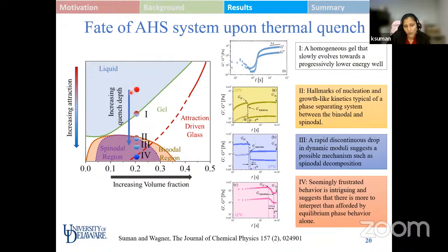As we increase the quench depth, we enter the two-phase region. In region 2, we saw a sudden decrease in the modulus value, followed by a continual increase in the modulus value, which suggests that continuous nucleation and growth-like kinetics is happening in the material, and therefore the material can be supposed to lie between the binodal and the spinodal region. With further increase in the quench depth, we enter region 3, where the sudden decrease is followed by an almost constant value of modulus, which suggests a possible mechanism of spinodal decomposition occurring and then having a firm viscoelastic behavior in the gel, which is demarcated by region 3 over here.